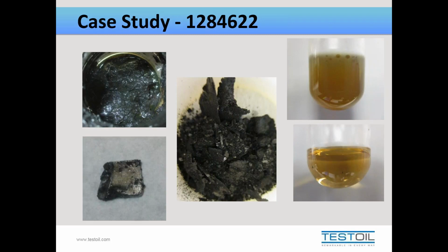And one of the big recommendations here was that it might have been worthwhile to consider investing in labyrinth seals if they weren't already in use. We never heard what exactly was being used, but it is pretty widely recognized that labyrinth seals have very good performance when compared to your standard lip seals. And that was really the big recommendation for this one. And also, routine testing on this may have been able to detect a silicone issue sooner.